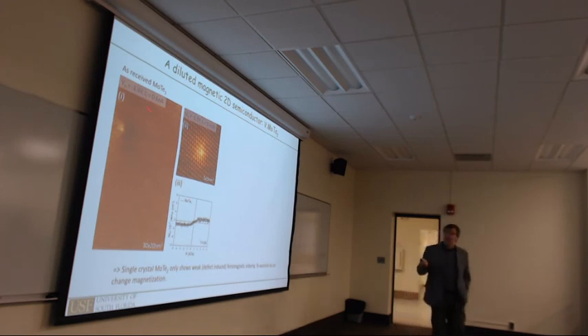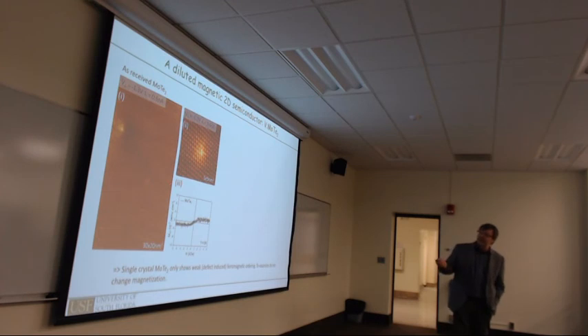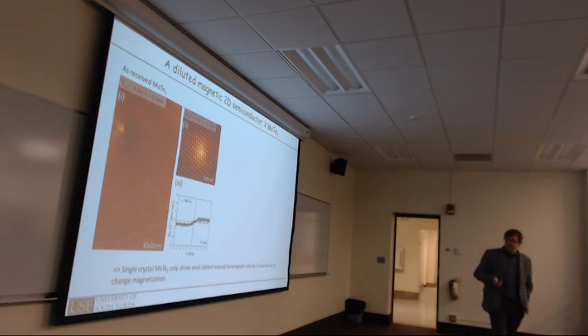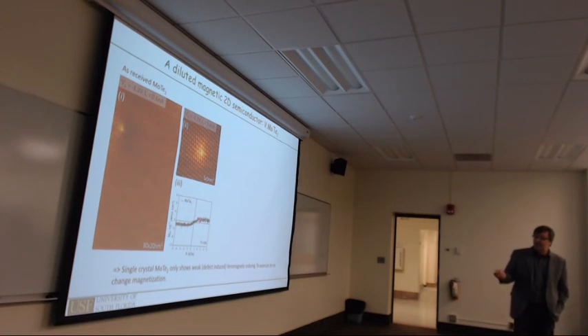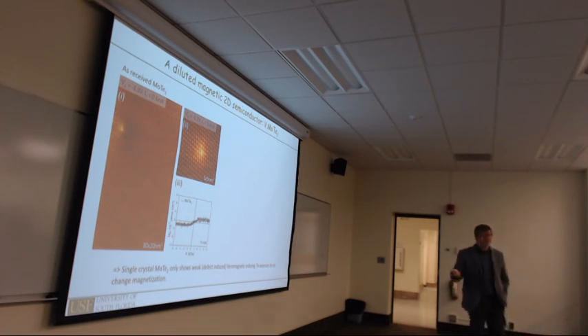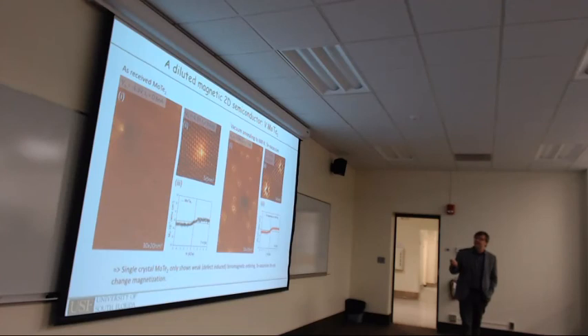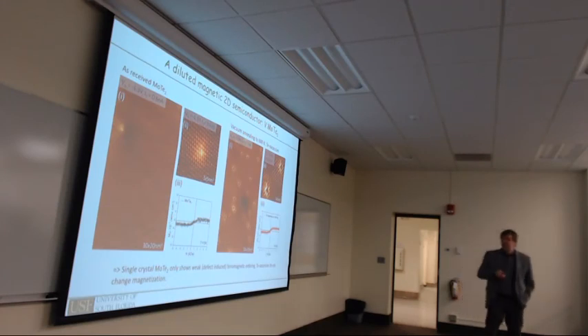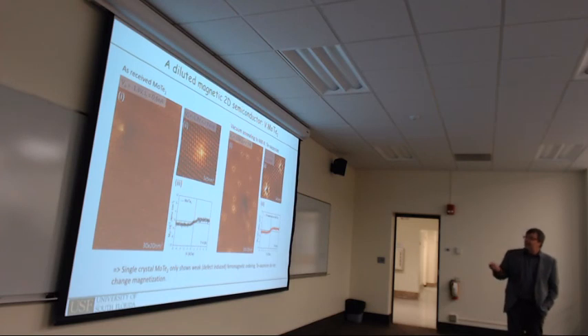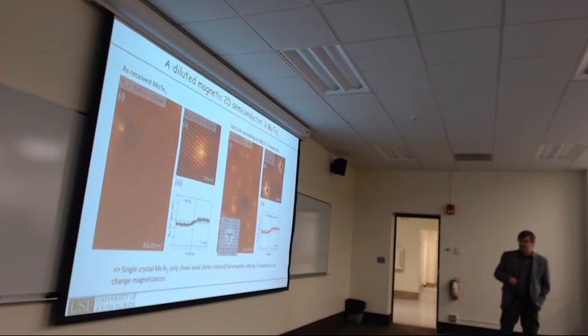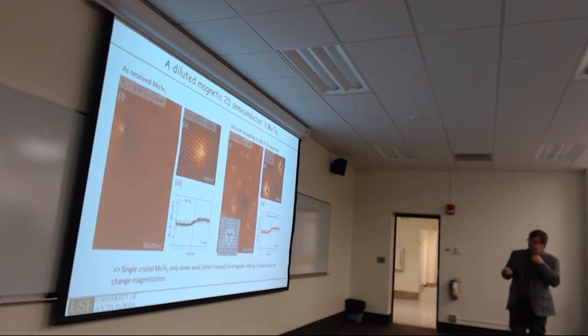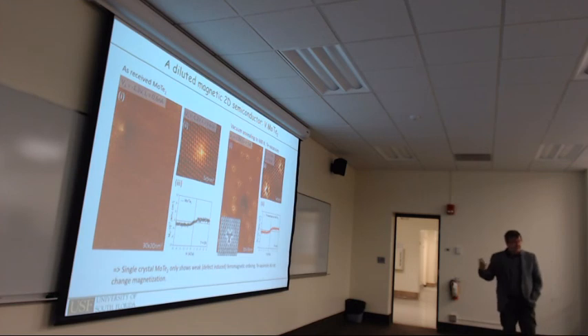So again, we started with a MoTe2 single crystal. There are some native defects, which may be molybdenum antisites, as some people suggest, but overall it's fairly defect-free. There's some weak ferromagnetic response if you do magnetization versus magnetic field measurements, just a hysteresis measurement, but it's really very weak. We can take that crystal and just anneal it in vacuum to 600 Kelvin, and what we start forming is what we think are tellurium vacancies, which show up nicely in STM images and correspond to simulated STM images. So at 600 Kelvin, we just dissolve some tellurium from the surface. But the magnetic signal doesn't really change.